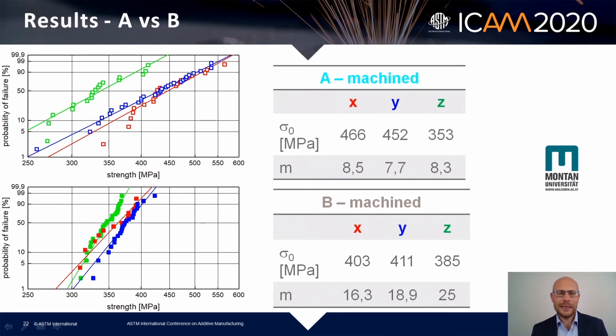But what you can see from the Weibull plot on the left hand side is that there is a clear difference between Z and the other two axes in the A sample, whereas we don't see a significant difference in the B sample. And also, as you can see from the Weibull modulus, in the B sample the Weibull modulus is much higher than in the A sample.